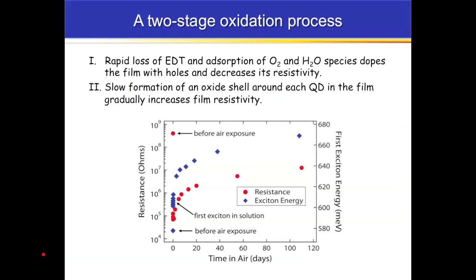And so we effectively think that we have a two-stage oxidation process. The first stage is very rapid loss of the organic molecule and absorption of the oxygen and water on the surface. This leads to heavy hole doping in lead selenide, and so we see a very large decrease in the resistance. This is before oxidation, and then immediately after oxidation, we get like a 1,000-fold change in the resistance.